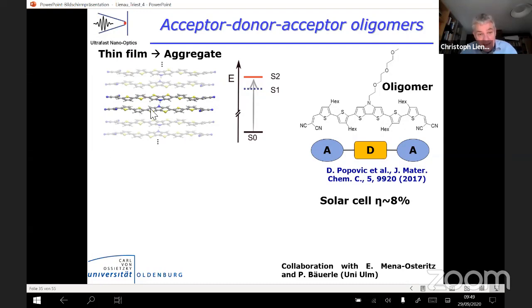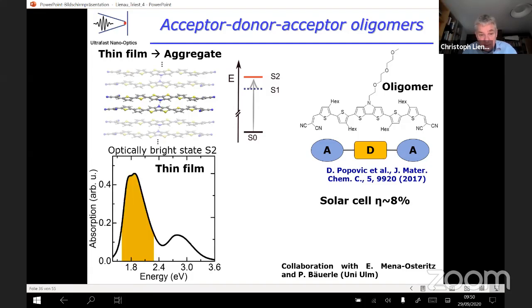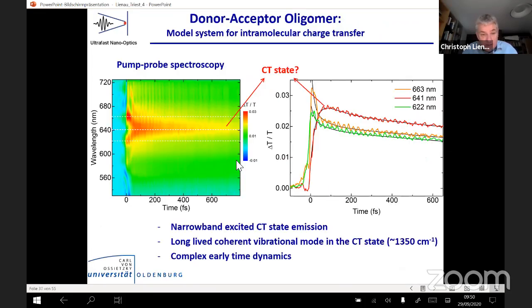And this antiparallel alignment of dipoles has the following consequence. In this case, it's not the lowest excited electronic state that is optically bright, but the second excited electronic state that is bright. This will become important in a second. Okay, but so the absorption spectrum from the thin film